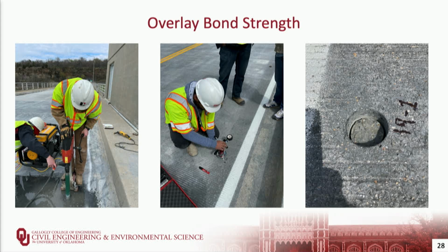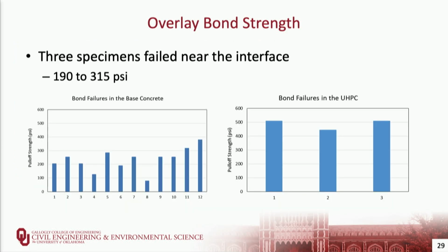So we cored sections through the overlay that we had marked previously so that we would get the thin 1.5 inch thick sections, not the half depth, 6 inch thick sections. We then glued steel pucks onto those cores and used a pull-off tester to measure the bond strength. And there on the right, you can see the end product of one of those tests. And if you look really closely, you can see the interface between the overlay and the base concrete.